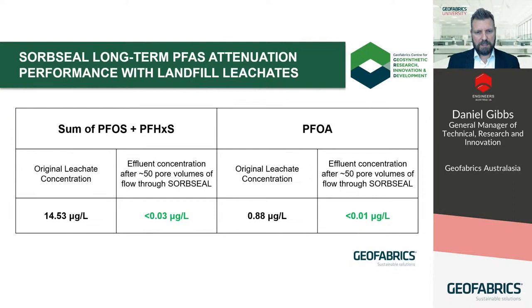So if we just focus on the three main long-chain PFAS nominated in the NEMP, we can see that SORBSEAL is able to reduce the originally high levels of PFOS and PFHxS, which were outside even the 7 micrograms per litre maximum for a double-line system, to just less than 0.03 micrograms per litre after 50 pore volumes of flow. Remember, this is permeated using actual leachate, and the conditions of the ASTM D6766 GCL permeability test method, representing 1.5 meters of simulated hydraulic head and a relatively low confining pressure.